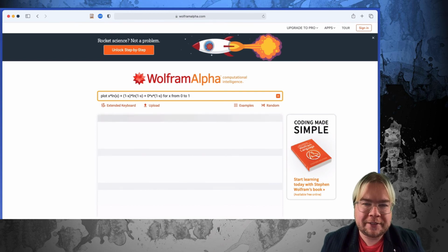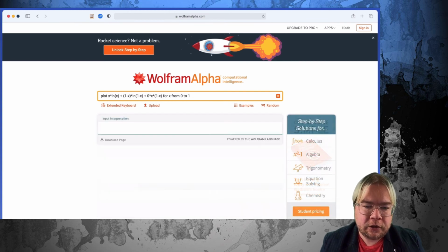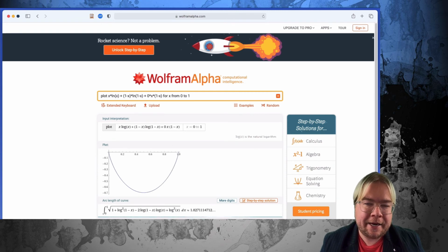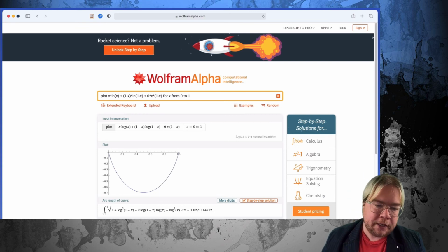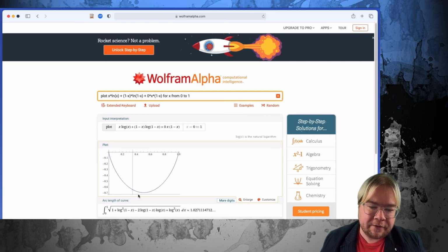And you kind of already saw what the curve is going to look like. So what I've plotted here, I've set NA and NB equal to 1. So this is a regular solution. And because chi is equal to 0, this is an ideal mixture. So here is the free energy of mixing divided by kBT. And you see that it's always negative throughout all of the possible volume fractions of A.